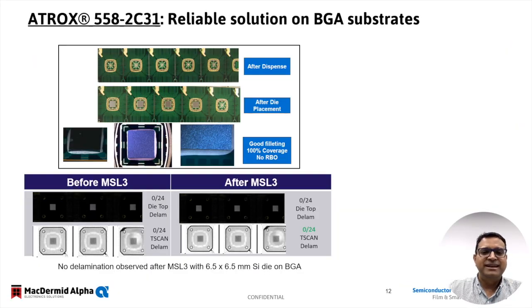Speaking about the versatility of this product, 558-2C31 has been demonstrated to have good workability, which provides consistent dispensing on organic BGA substrates. It also provides good fillet formation and die coverage, which are critical to provide adequate protection to the die when it is exposed to stress environments for testing like MSL3 testing on a large die shown in the bottom of the image. Here you can see that after the MSL3 exposure, we see no signs of delamination, which indicates high reliability.